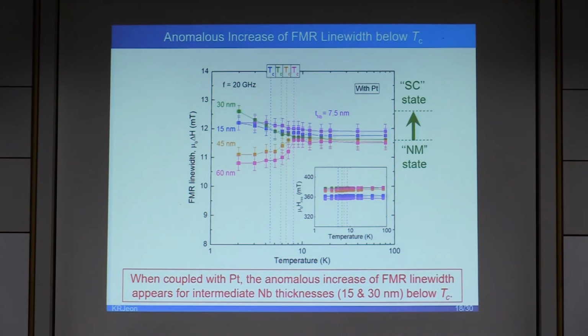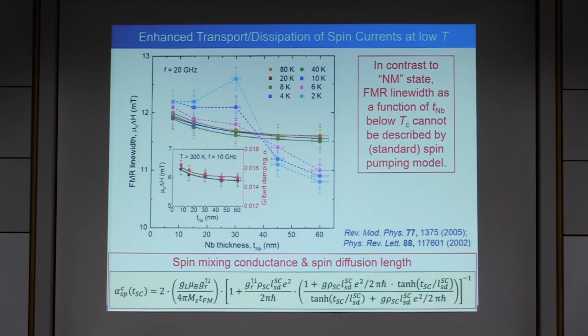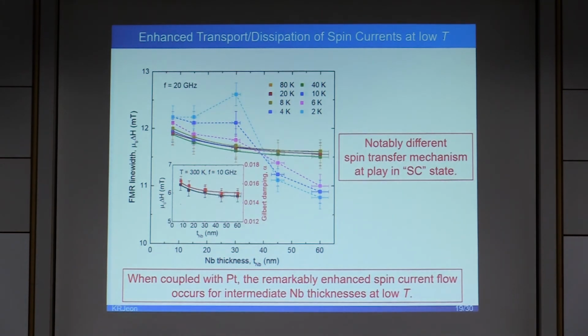For the thinner or thicker superconducting layers, the temperature dependence of FMR line width is qualitatively similar to the sample without the platinum layer. Intriguingly, in contrast to the normal state, the FMR line width as a function of niobium thickness below Tc cannot be described by standard spin pumping theory, indicating that a notably different spin transport mechanism is at work in the superconducting state.